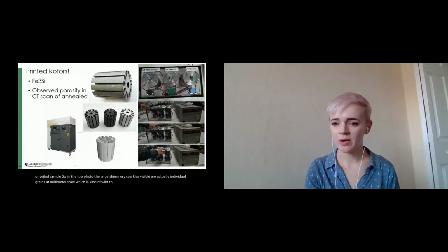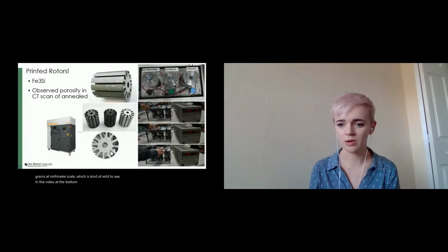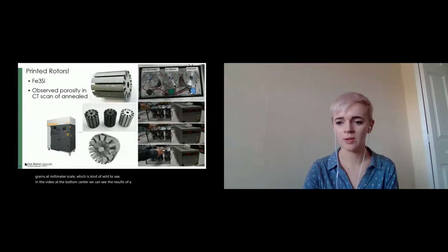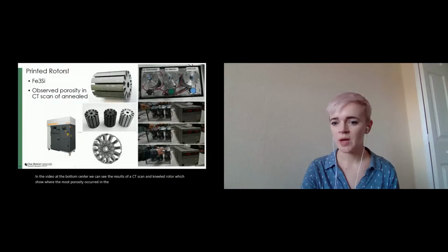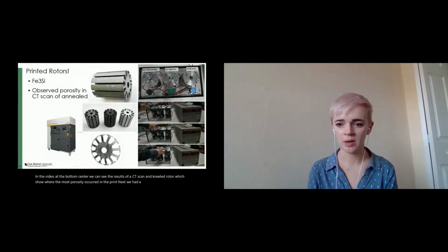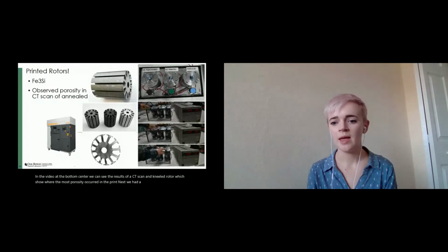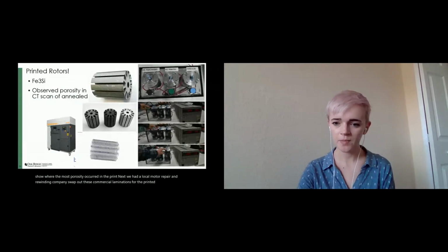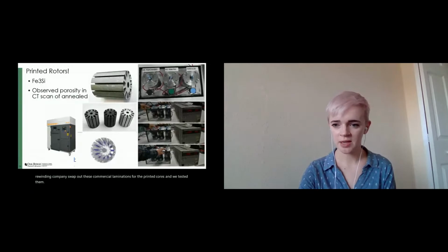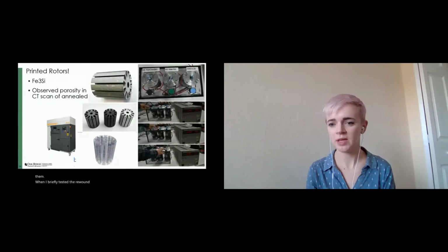In the video at the bottom center, we can see the results of a CT scan of an annealed rotor, which show where the most porosity occurred in the print. Next, we had a local motor repair and rewinding company swap out these commercial laminations for the printed cores, and we tested them. Now, when I briefly tested the rewound motors, I noticed a few key things.